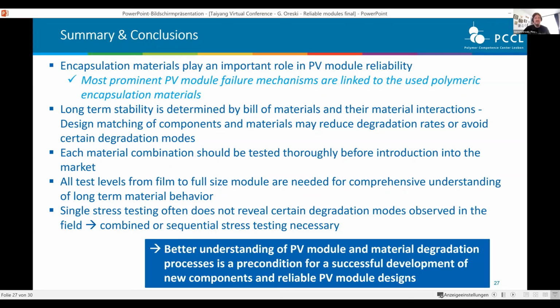And my speaker before mentioned PID, for example. But each material combination should be tested thoroughly before introduction into the market. So really do your testing, do your homework, and then you usually should get high quality modules. And all test levels from film to full size modules are needed for a comprehensive understanding of the long-term material and module behavior. And most important, single stress tests are good and you can learn something from them, but very often they don't reveal certain degradation modes which are observed in the field. So we need combined or sequential stress testing in order to reveal these degradation modes. Overall, I can just say we need a better understanding of the module and material degradation modes. And this is a precondition for a successful development of new components and reliable PV module designs.